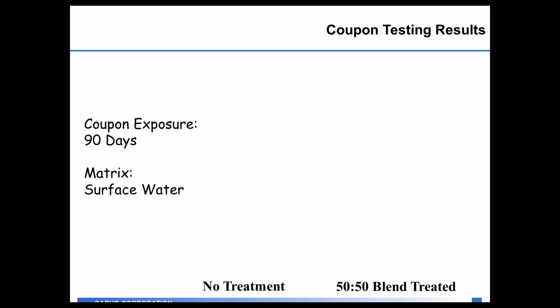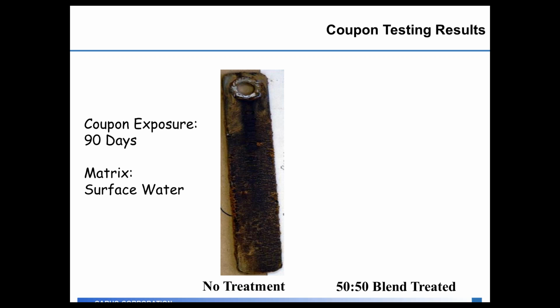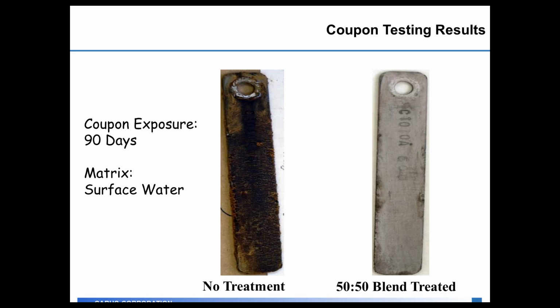When we look at the coupons, you're obviously going to get some numerical data, but you can also physically look at the coupons when you put them in and pull them out. In this case, this was a coupon exposed to Florida surface water for 90 days, and this was the mild steel coupon, and you can see the rust and scale that had formed on the coupon itself with no phosphate treatment. The coupon to the right was treated with 50-50 poly-ortho blend, and you can actually read the coupon number on it, and you have a little bit of formation of rust on the sides of the coupon, but physically you can see that the treatment change made a very drastic difference to the water quality.